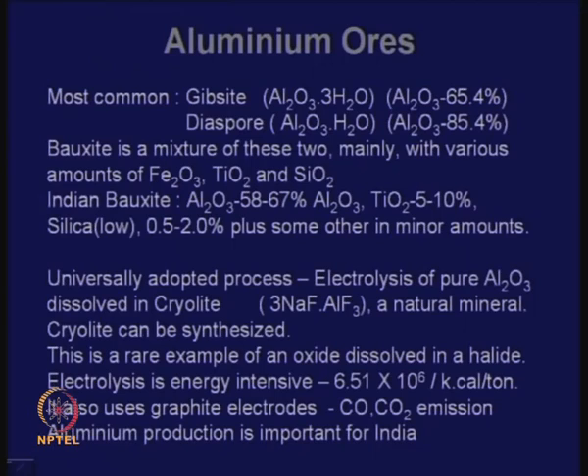Why is a halide as a solvent important? Because alumina can dissolve in a slag, but slag will be a viscous thing, it will not be easy to electrolyze. Whereas, cryolite is a salt in a molten state around 980 to 1000 degrees, alumina will dissolve in that, and will electrolyze to get aluminum. It is very energy intensive, about 6.5 x 10^6 kilocalories per ton is required. It also uses graphite electrodes, so it will produce a CO2 emission problem. There is no answer to these problems. People are trying to find answers, and I will try to tell you what kind of answers people are looking for.